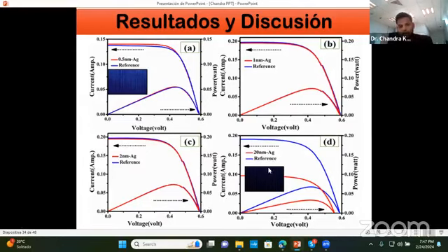But if we are talking about the 20 nanometer, see the color is getting black because a thicker film doesn't have the tendency to enhance the efficiency. And see here, blue indicates the reference, and 0.5 is above it in red, meaning short circuit current is increasing. That means solar efficiency could be enhanced.